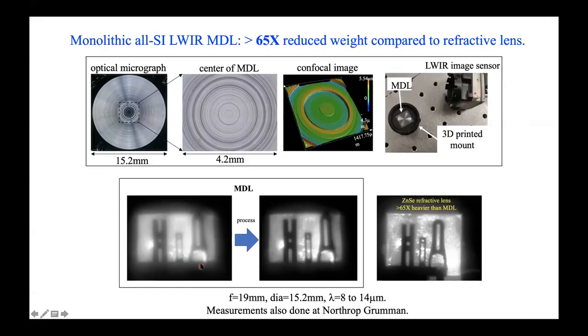What's really interesting is with some relatively simple post-processing, in this case, just very standard conventional filtering, you get images that are pretty comparable to what one could obtain from a zinc selenide refractive lens. By the way, this is a corrected refractor, so it's not a single surface or a two-surface lens, but it's got several elements in it. I think it's either a doublet or a triplet. But it's about 65 times heavier in comparison.